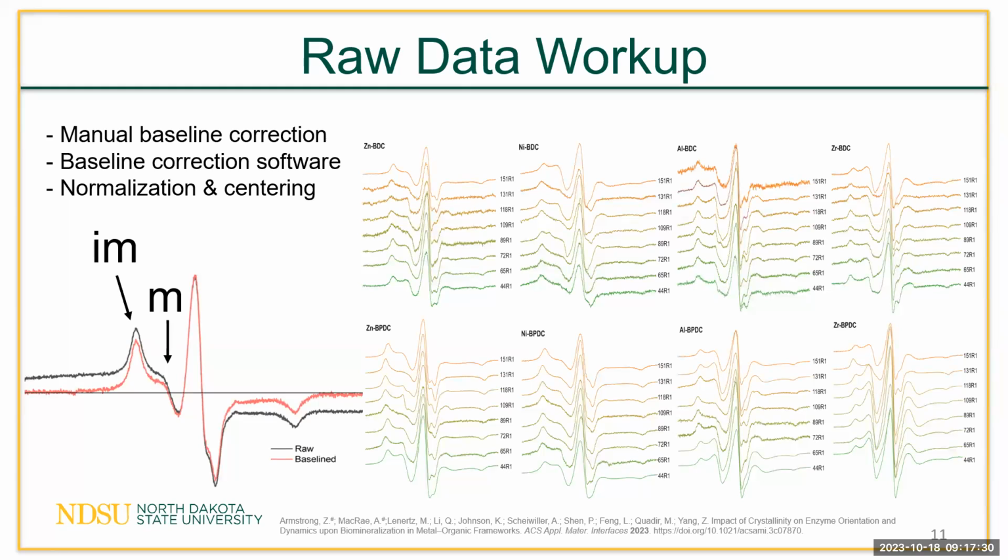copper MOF without protein from the protein and MOF combination, for most of them, it was just too much copper that once we removed and baselined out, or blanked out, the copper, we actually didn't see any MTSL spin label peaks. And this is likely due to the high concentration of copper compared to the very low concentration of 1 MTSL spin label per protein, and we're not getting a ton of protein compared to copper in these solutions.